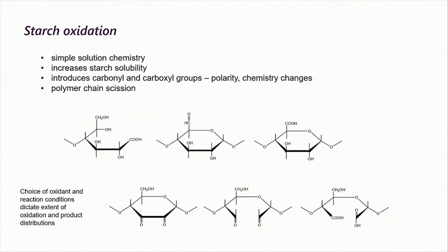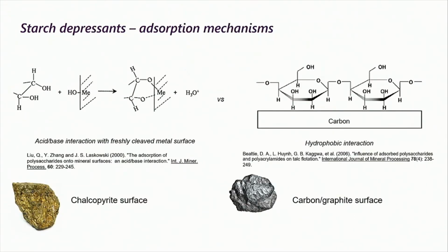The type of functional groups you can get, like I said, goes from the hydroxyl to the carbonyl to the carboxyl, but where it happens is all dependent on the reaction conditions you prepare the oxidized starch in. So you can see you get different combinations of ring open with carboxyls, carbonyls, aldehydes on the C6, or carboxyls on the C6, or you can get dialdehydes or diketones. So there's quite an array of different types of functionality that you get in starch, just with oxidation. It's one of the simpler, I suppose, reactions you can carry out.